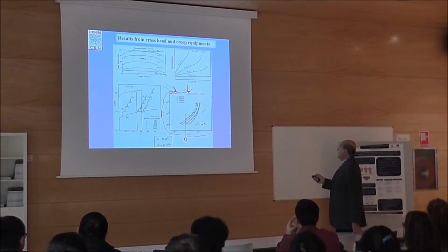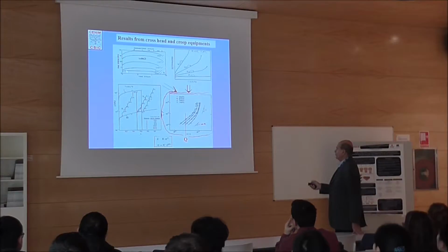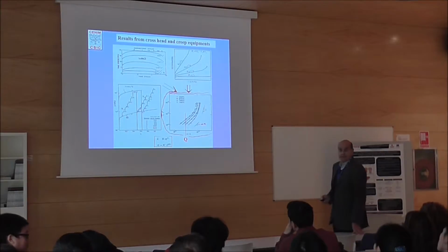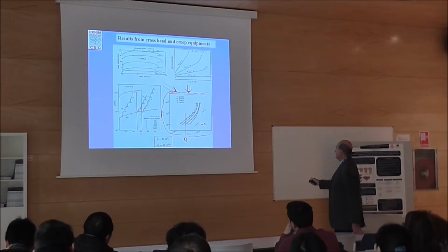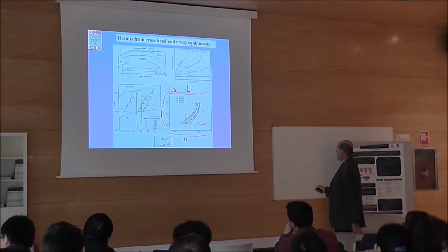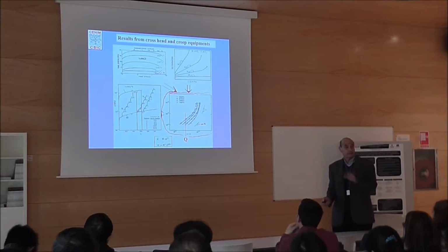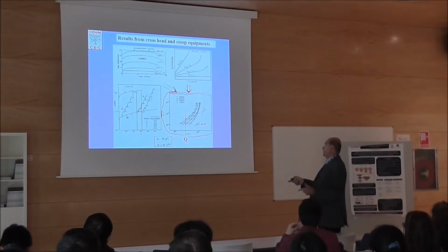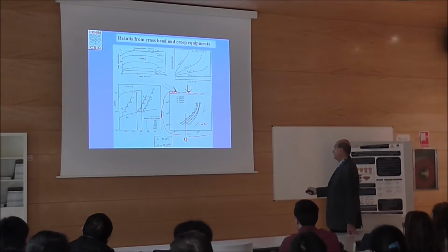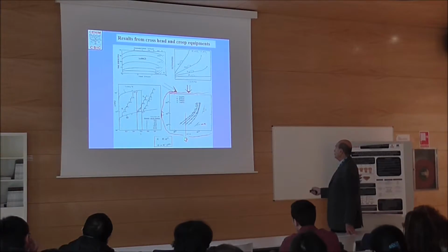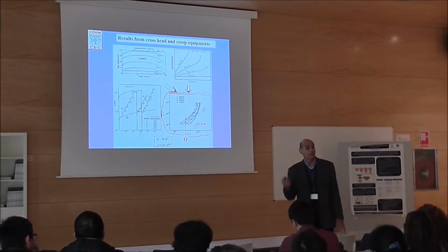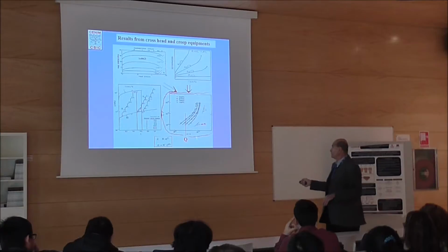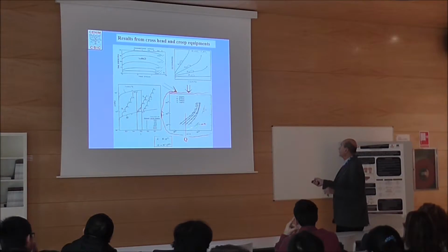Just to finish this part, in this case, you have a cross-head machine. You have different strain rates, and you get the stresses. And here you have different stresses, and you get the strain rate. All of them will go to this type of graph, and here the slope of this curve is the stress exponent. Very important to get this stress exponent, which is the inverse of the strain rate sensitivity exponent. So 1/n here is the other one, the inverse. And the distance between these curves is proportional to the activation energy for creep. For creep, nothing to do with diffusion, just for creep. So for every single material, we can determine these two important components, N and Q.